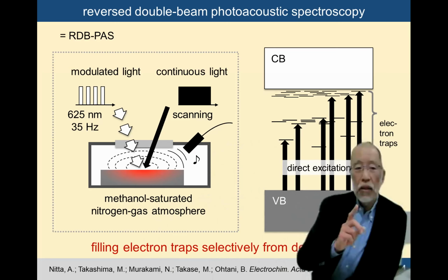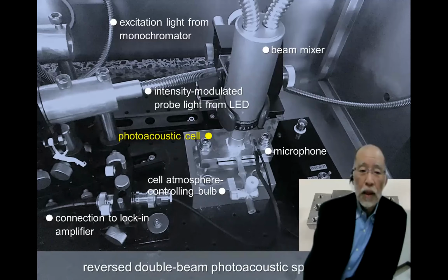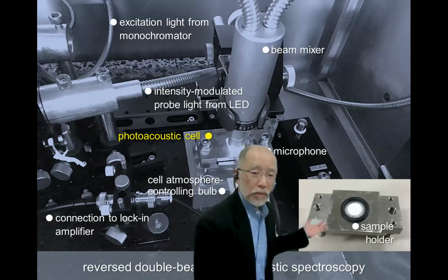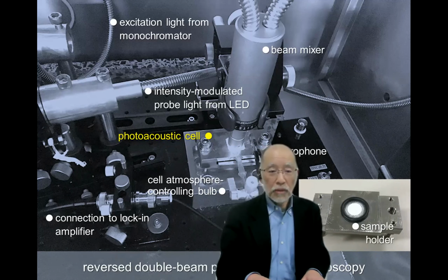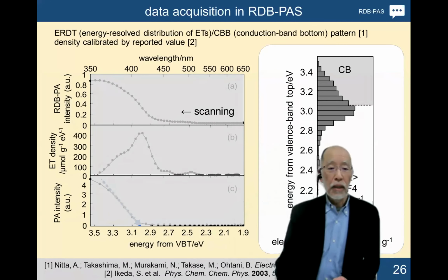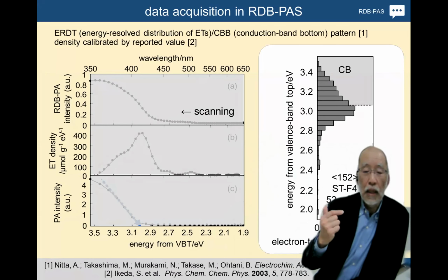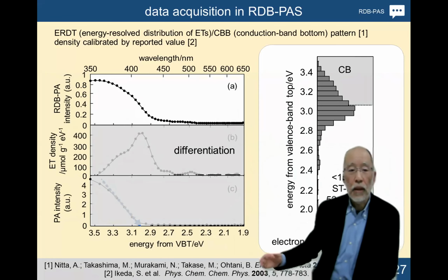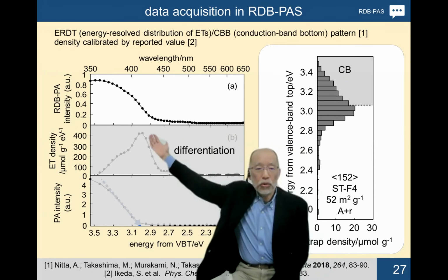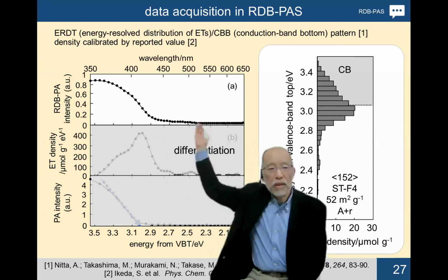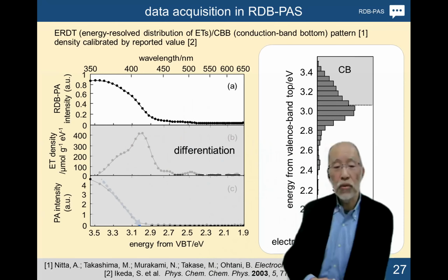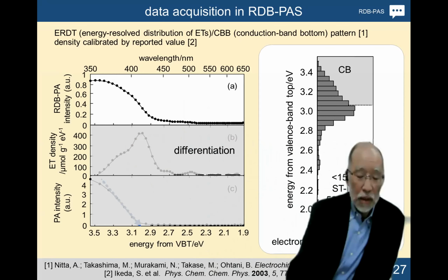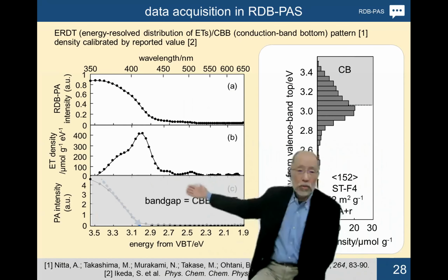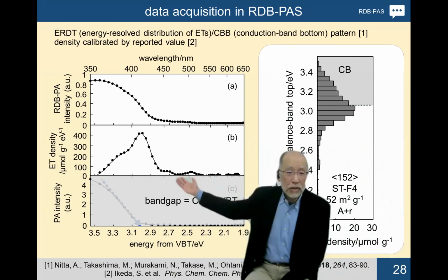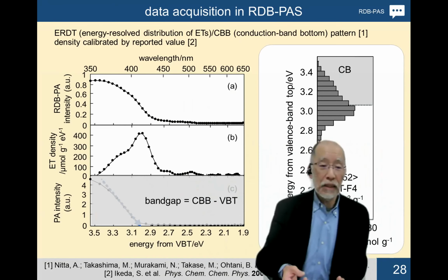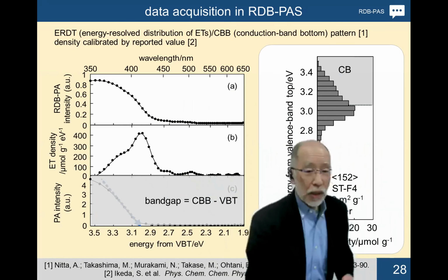So this is the newly developed reverse double-beam photoacoustic spectroscopy. And this is a real setup. The sample holder is almost the same as for XRD, and powder samples, thin film samples, and bulk samples can be measured. The top left is the photoacoustic signal obtained by scanning the excitation light from the longer wavelength side to the shorter wavelength side. Here, the new absorption appears and keeps increasing. This is the accumulation of electrons in electron traps. That is then differentiated to give the energy-resolved distribution of electron traps on a relative scale. And this relative amount is converted into an absolute value by comparison with the chemical titration method.